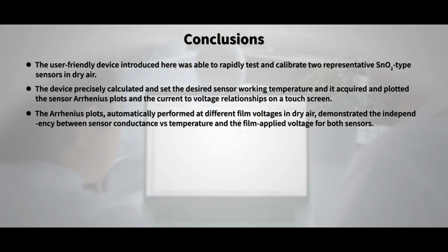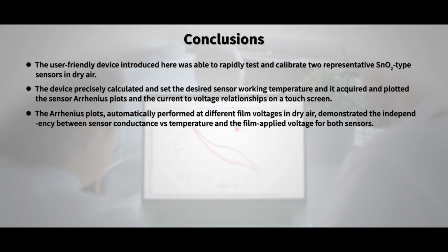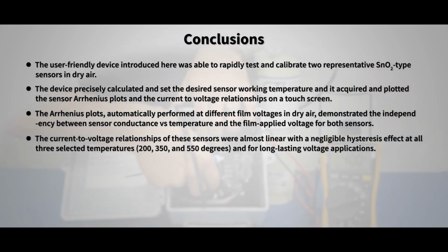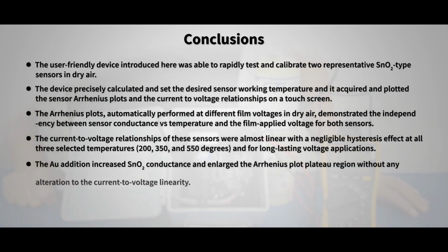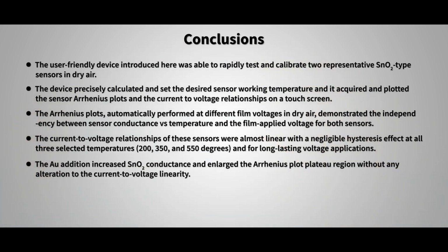The Arrhenius plots, automatically performed at different film voltages in dry air, demonstrated the independency between sensor conductance versus temperature and the film-applied voltage for both sensors. The current-to-voltage relationships of these sensors were almost linear with a negligible hysteresis effect at all three selected temperatures and for long-lasting voltage applications. The gold addition increased tin oxide conductance and enlarged the Arrhenius plot plateau region without any alteration to the current-to-voltage linearity.